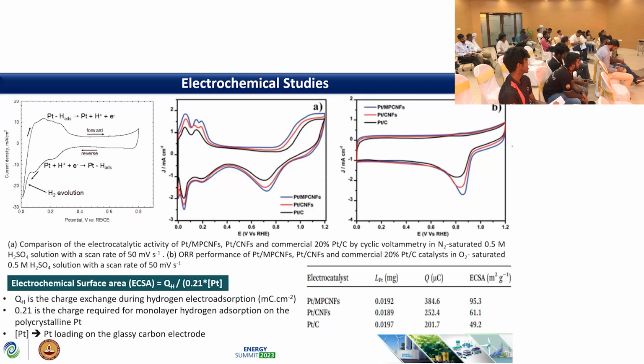So we could observe nice hydrogen adsorption and desorption peaks, and from that we derived the electrochemical surface area from the hydrogen adsorption peak using this formula. We understood that for mesoporous carbon nanofibers, the electrochemical surface area was around 95.3 meter square per gram, which was almost double that of the commercial PTC.